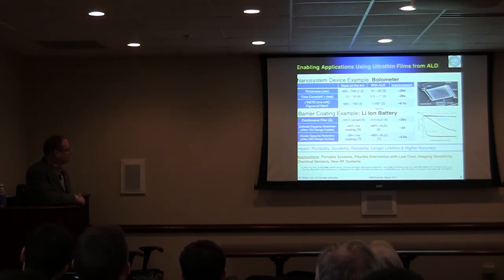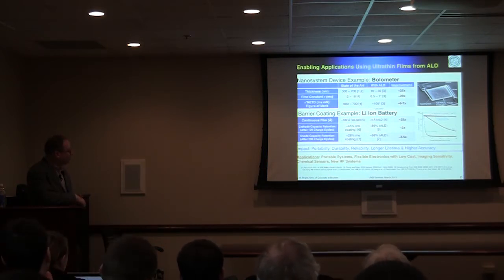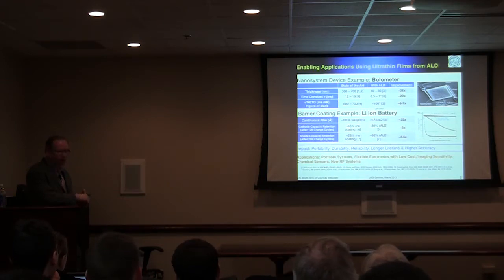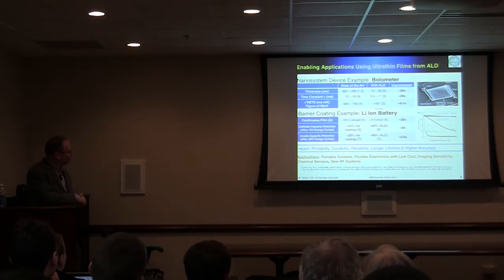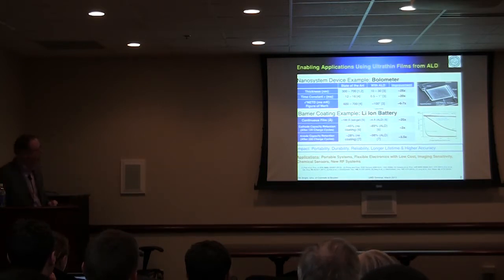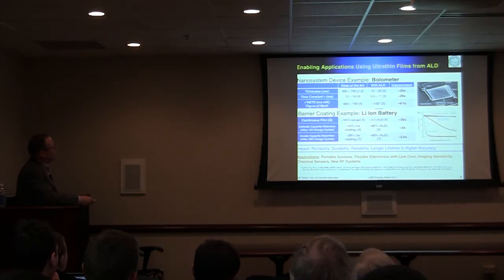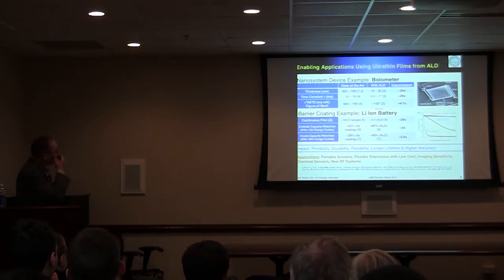The example shown here is from Professor Si Lee's group in my department. He works on solid-state electrolyte batteries, and they use ALD for coating nanoparticles to keep the nanoparticles stable. The graph you see on top shows the discharge cycles, typical cycles, and then once coated with ALD alumina, you can see this curve right here. So you get better performance there.